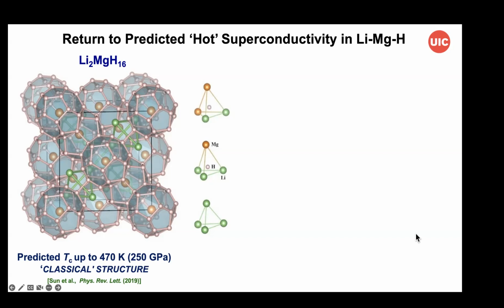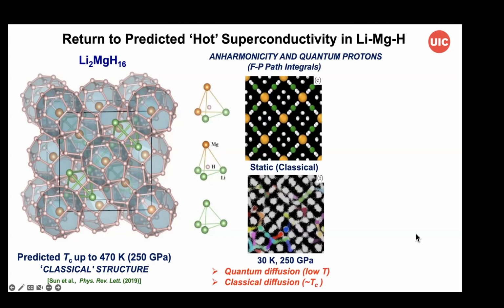basically quantum diffusion. So this motivated a series of calculations, both classical and path integral calculations, to look at these two effects. And in fact, what we find is that at high temperatures, one has diffusive motion, rather extensive diffusive motion, very much like what you see in many other hydrides that aren't superconductors. And this is in the vicinity of the TC, and at low temperature, you can see this persist in a sense in terms of quantum diffusion.